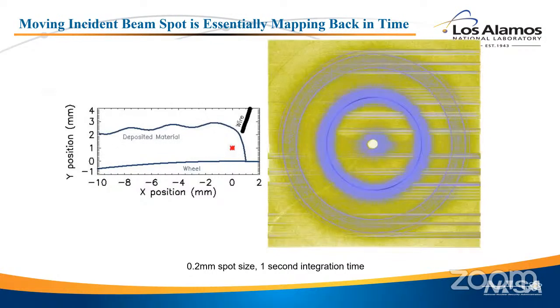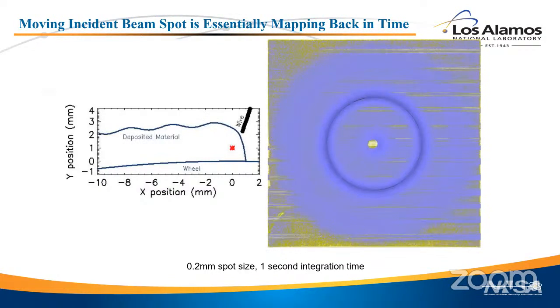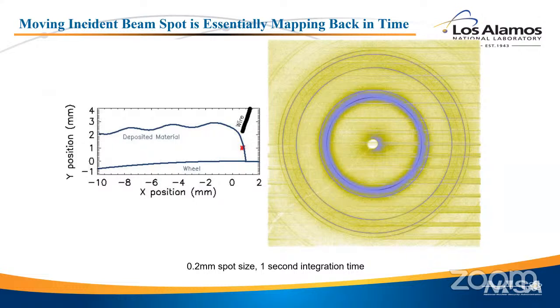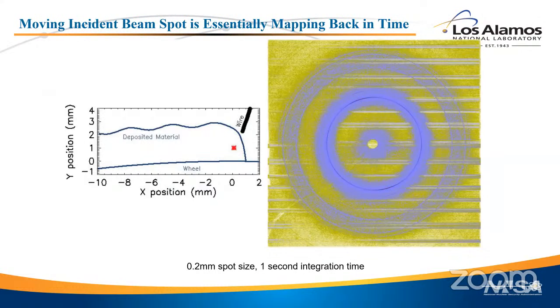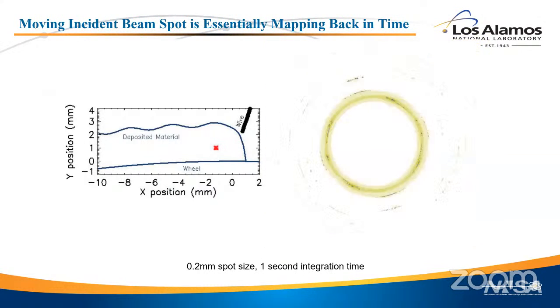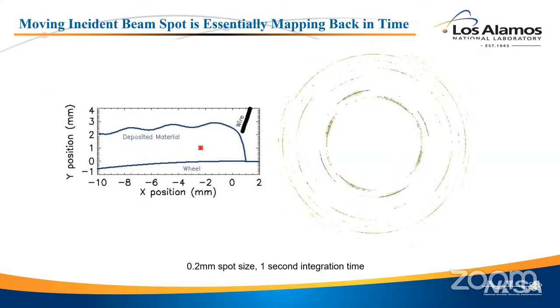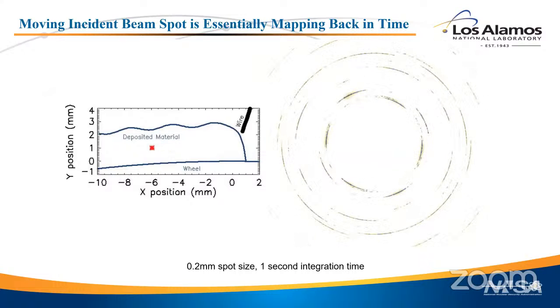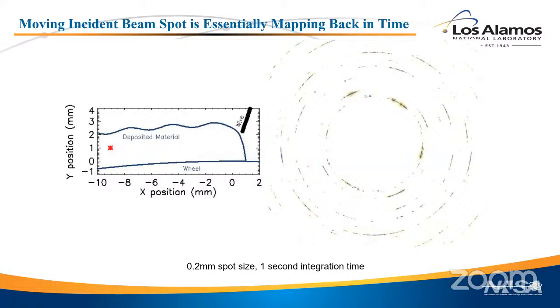So this is a bunch of diffraction patterns that we collect during a weld. There's liquid, you see the broad rings, and there you see the sharp rings, that's solid. You see coexistence of liquid and solid, and now it's fully solidified. You see the rings, but they're not complete rings. And if you look closely, you'll see there's symmetry to the rings. That's the crystallographic texture. As it solidifies, certain grain orientations are preferred, right? There's a crystal growth direction, and that shows up in how the intensity varies as you go around those rings.